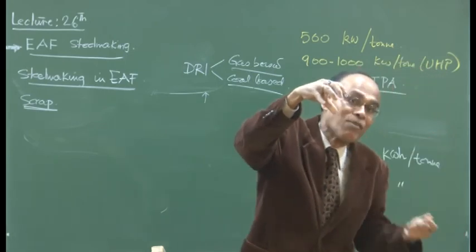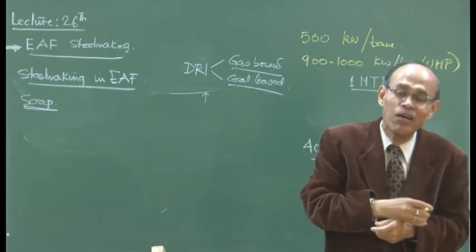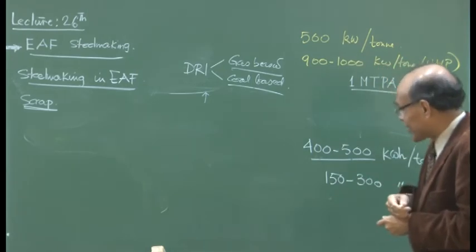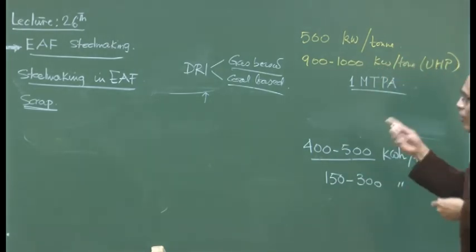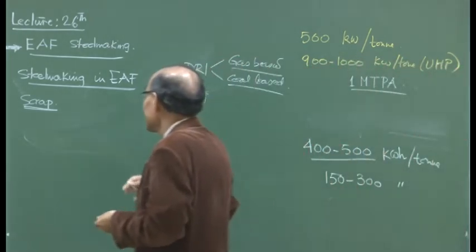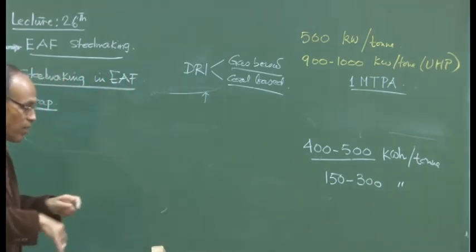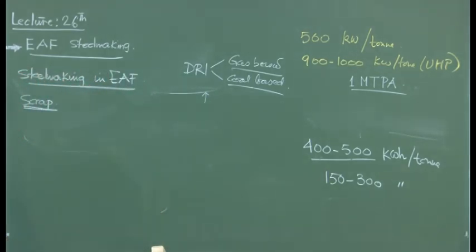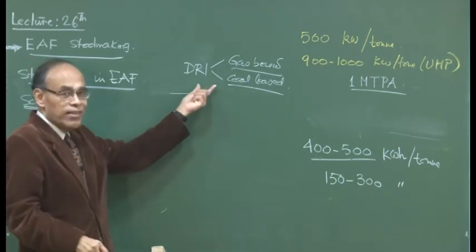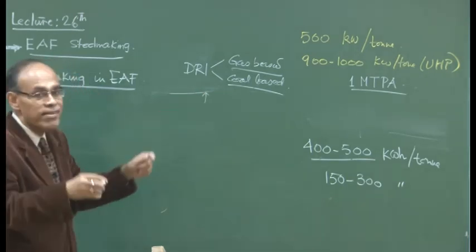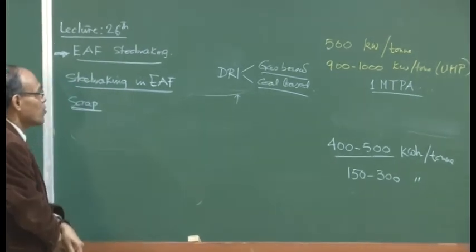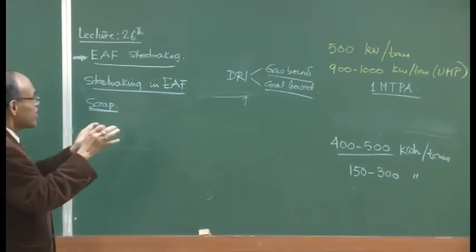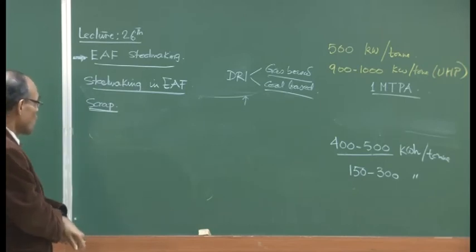So, it will prevent the further oxidation of melt iron, and thereby it can ensure that the dissolved oxygen level in the bath is now a little bit smaller. So, whatever oxide materials are present in the DRI, most of them will try to go into the slag, barring the iron oxides, a part of which can get reduced also.